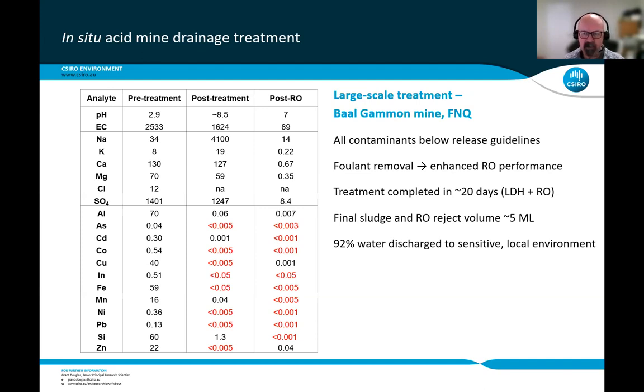So really, as I tried to emphasise earlier on, a broad spectrum removal of a whole range of contaminants of quite widely different chemistries. And as I alluded to earlier, we had foulant removal, all of those usual suspects in terms of foulants, and that really did give us very much enhanced RO performance. The RO was able to breathe effectively. The treatment of this pit was completed in about 20 days, that was both formation of the in situ layered double hydroxide and the RO.